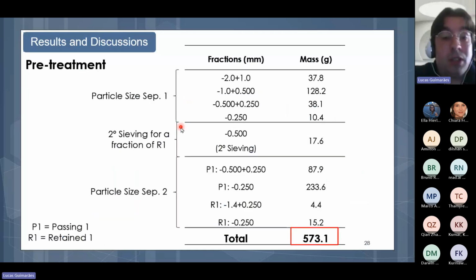The pre-treatment, after the 2 millings with knife mills and particle size separations, resulted in a black mass, let's say, proper to use for the next step of leaching, a mass of 573 grams. And it's important to highlight here that with this pre-treatment, all the separators, all the plastic and all the external metal structure of the batteries were completely removed, and the great majority of copper and aluminum metallic of the current collectors were also removed, with just a little bit remaining here in the black mass.